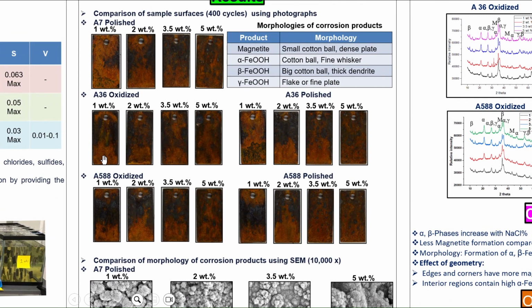A7, A36, and A588 samples are shown here, and every sample has two colors, black and orange. The black color region is for magnetite and orange is for alpha or beta FeOOH. And we can see that black is present usually at the edges or corners, and orange is at the center or interior regions. So we can say that the magnetite is usually at the corners and the edges, and the interior has alpha and beta FeOOH.